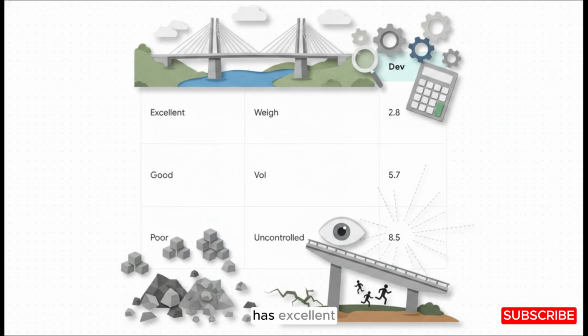When a site has excellent control, meaning they're using precise weigh batching and continual supervision, the variation in the concrete's strength, the standard deviation, is super tight, just 2.8 MPa. But look at the bottom row. If the site is uncontrolled, just eyeballing volumes of aggregate with little supervision, that deviation jumps all the way to 8.5 MPa. That level of uncertainty is honestly terrifying when you're building something like a massive bridge.